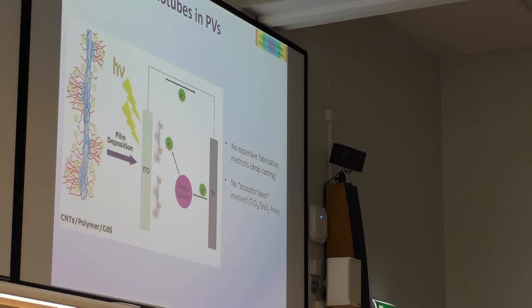You don't need any acceptor layers like titania or tin oxide. The nanotube will be the acceptor. The nanoparticles, or the photosensitive light harvesting units, will be the electron donor, just spin coated, and this is basically a new photoelectrochemical cell to provide energy.